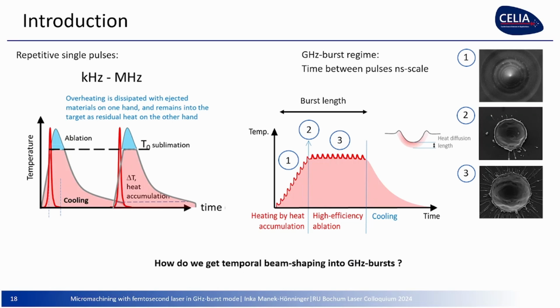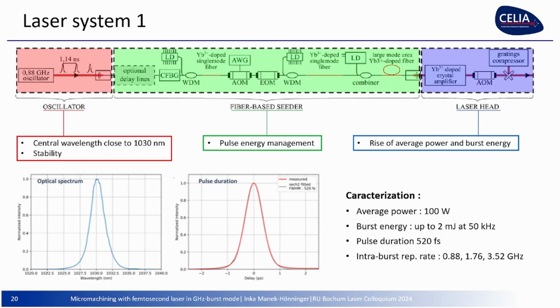So, how do we do our temporal beam shaping, forming bursts? That leads me to show you the laser system from Amplitude. In this first version, there is a gigahertz oscillator working at 0.88 gigahertz, which means there's 1.14 nanoseconds between each pulse. It's a pulse train oscillator. It's ytterbium-based, so it's lasing at 1030 nanometers, around 1 micron, with a very stable, small cavity at this repetition rate.